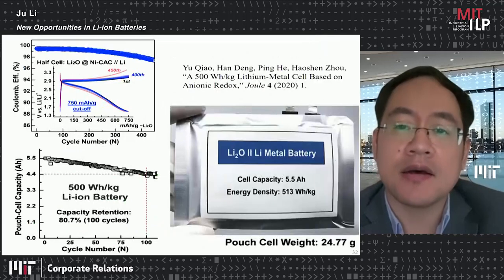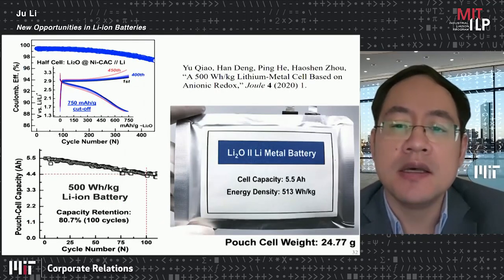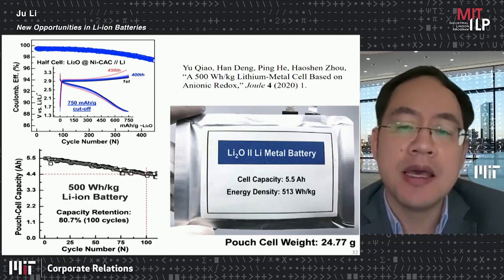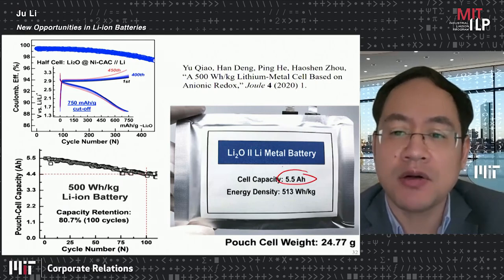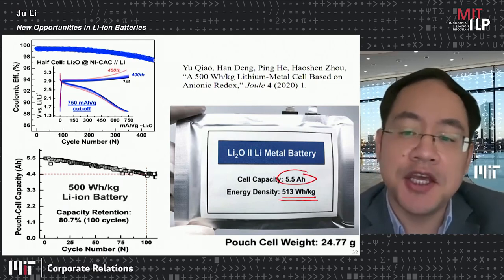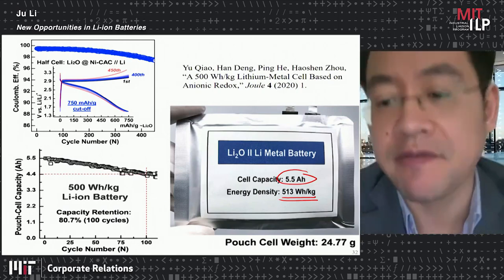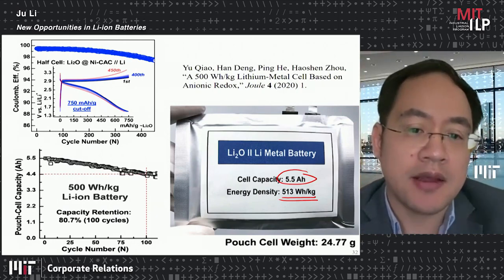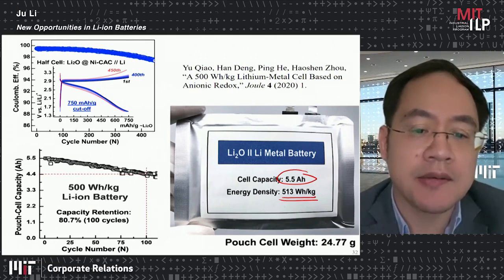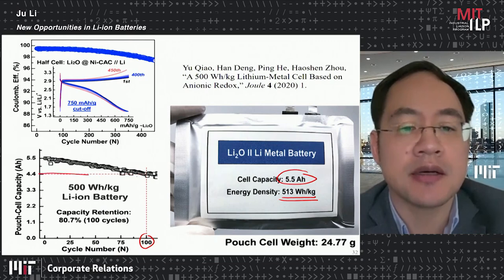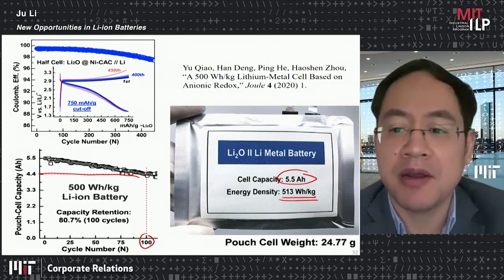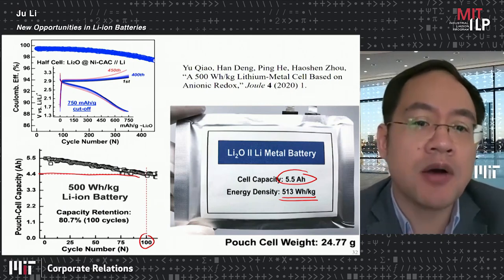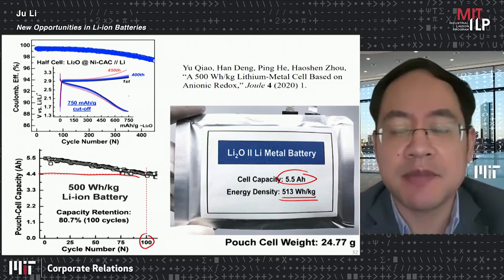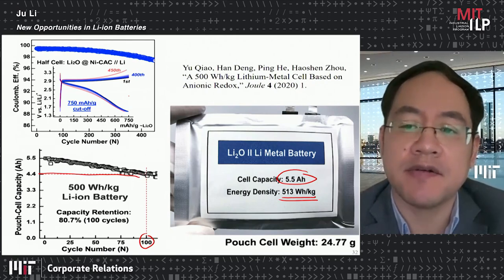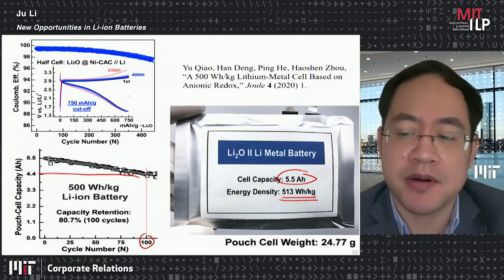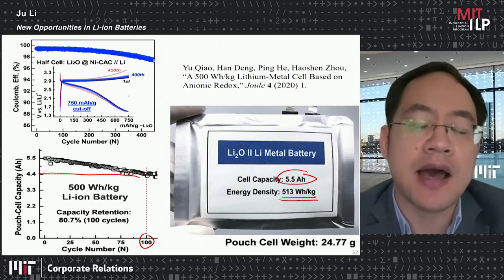So just this week, we've seen this pouch cell result from the same group, where they've made a 5.5 amp-hour pouch cell with initial energy density higher than 500 watt hour per kilogram. And I think even down to 100 cycles, they can still keep about 400 watt hour per kilogram. So this is the half cell, but they have shown the pouch cell charge discharge curve in their paper.